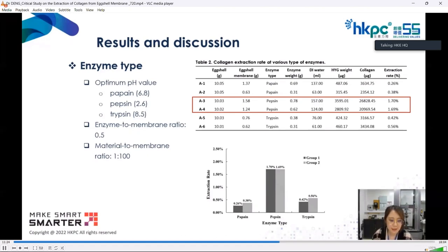It was found that the optimal pH values of pepsin and trypsin were 2.6 and 8.5, respectively. The enzyme-to-membrane ratio and material-to-water ratio were set to 0.5 and 1 to 100. The results are shown in Table 2.